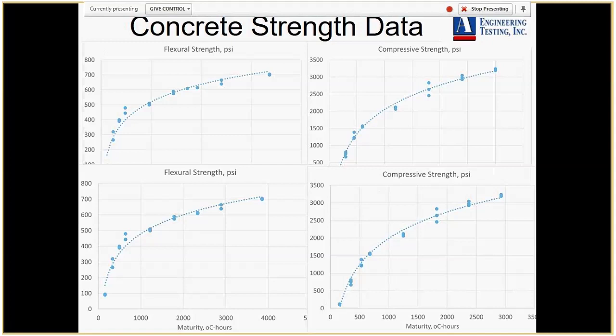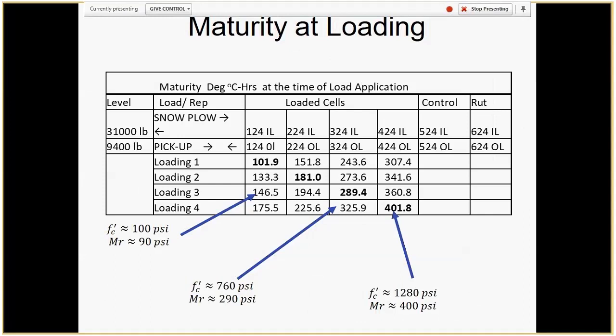But the top plots were given under more or less constant temperatures, and if we convert it to maturity, so basically it's a summation of the time above reference temperature, a summation of the temperature above reference temperature for each hour, then in this case, that strength development can be applied to any temperature regime after placement. In this case, we can convert time of loading into the maturity of loading and estimate strength here.